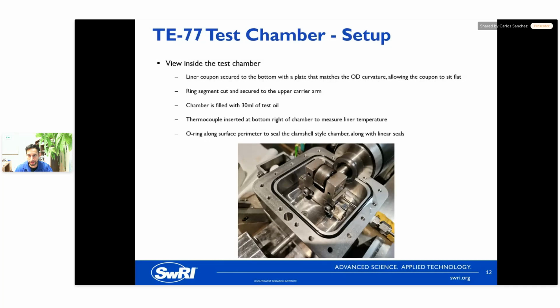The chamber is filled with 30 milliliters of oil, whatever oil that we're testing with at the time. And there's a thermocouple at the bottom that can monitor temperature. We can run tests up to 100 degrees Celsius in this case. And like I mentioned, there's all kinds of O-rings and seals set up throughout the chamber that help keep the hydrogen in place.